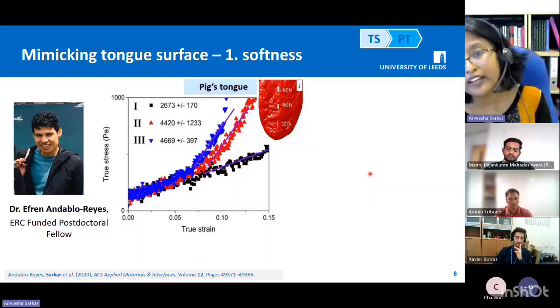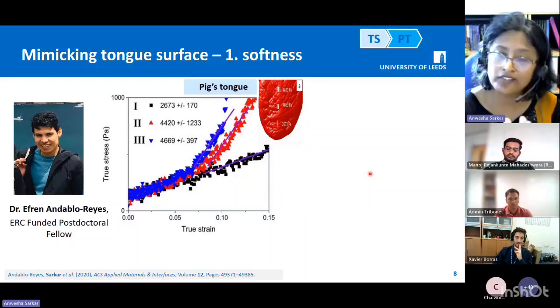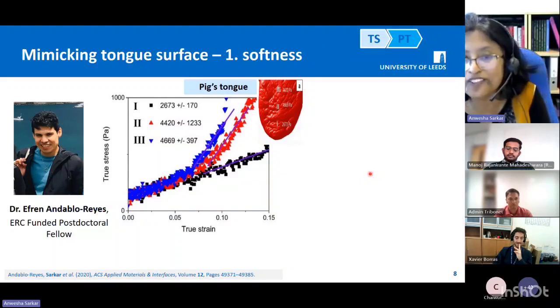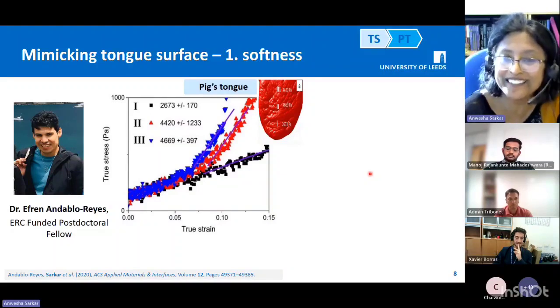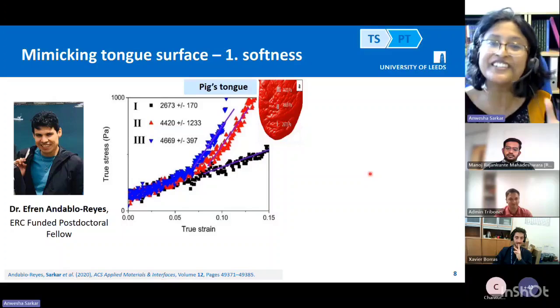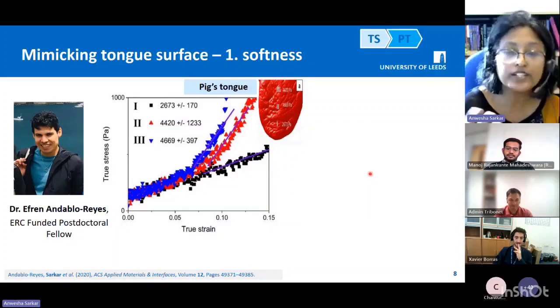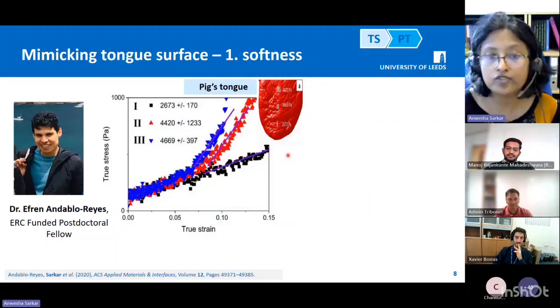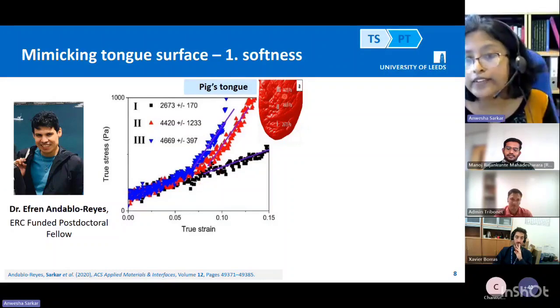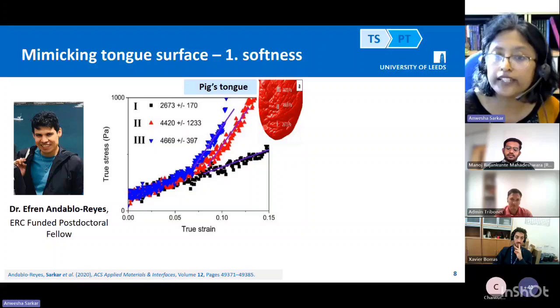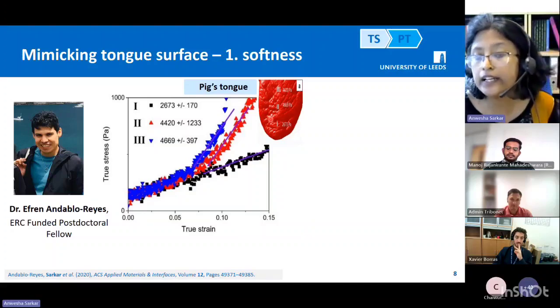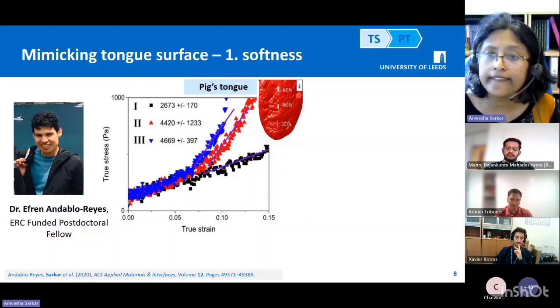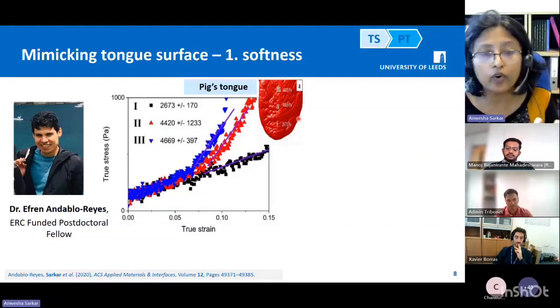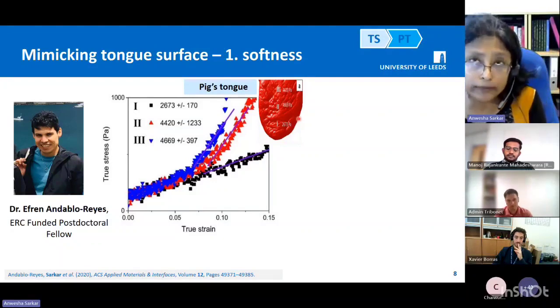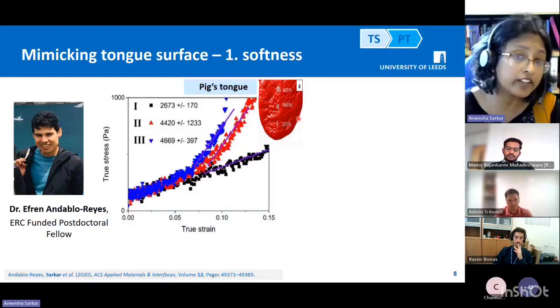So what we did, we took the closest proxy, which is a pig's tongue, because we, of course, can't ask a human being to donate their tongue for this work. So we took pig's tongue and we measured its deformability. So this is a true stress strain diagram. And what you can see is, irrespective of wherever you take the analysis, they essentially are in the order of 2 to 4 kilopascal. So they are very, very, very soft.